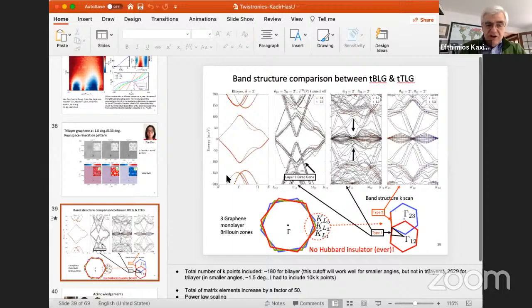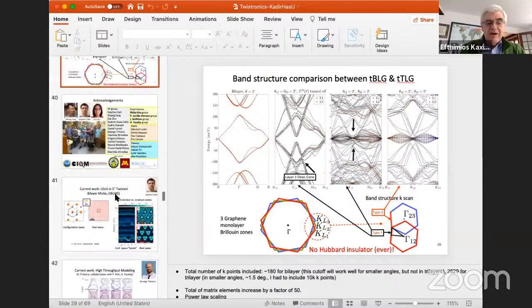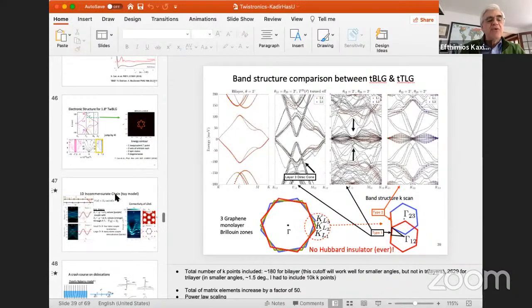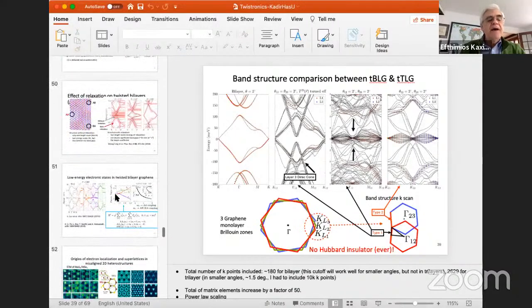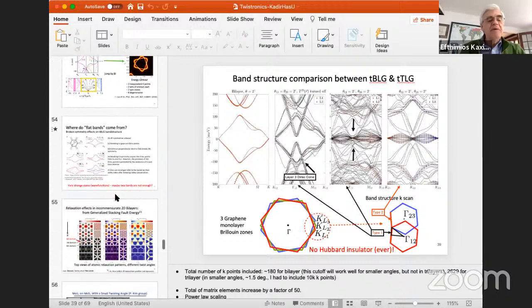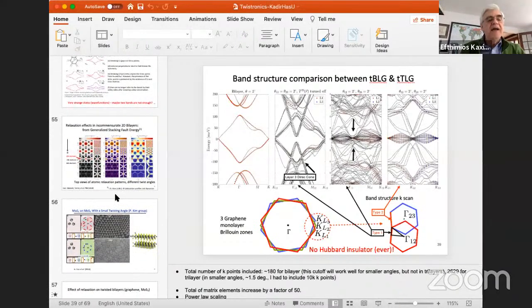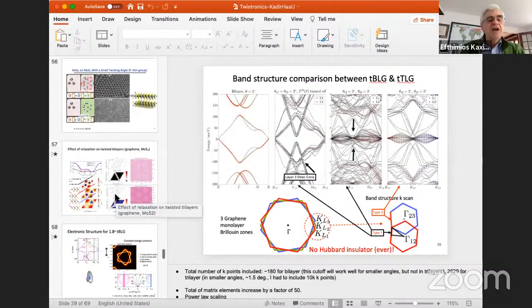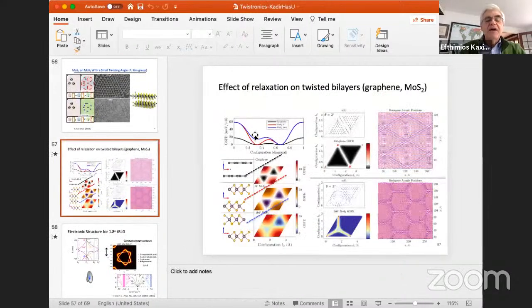And this is not trivial to do because of the very large number of atoms, as you mentioned, but we have a very special way of doing that that I didn't have enough time to describe. So let me just very quickly outline what happens. So essentially what we do is the following. So it's shown here schematically. You take one ideal layer, no twist, and you put on top of it another ideal layer, no twist, very small unit cells, and you slide the two relative to each other. And by sliding, you explore all these possible energy landscapes.